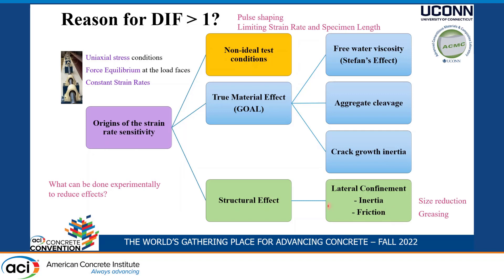To minimize inertia, we can use smaller specimens, though it is always present to some degree. Applying grease to the load faces and bar interfaces works very well to reduce friction, dropping it close to zero. For non-ideal test conditions, pulse shaping — using a shaped striker or a different material disc in front of the bar — can help achieve near-ideal conditions, though there are limits on achievable strain rates and specimen length constraints.